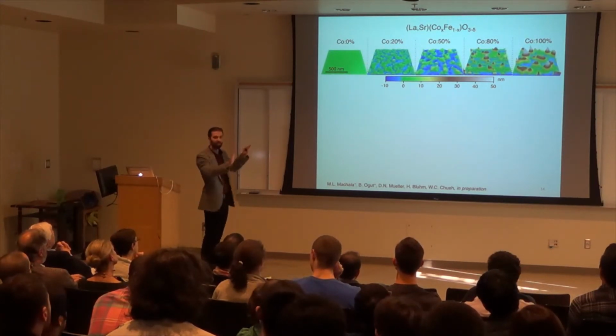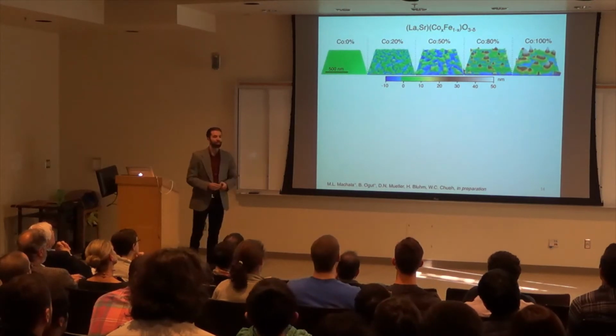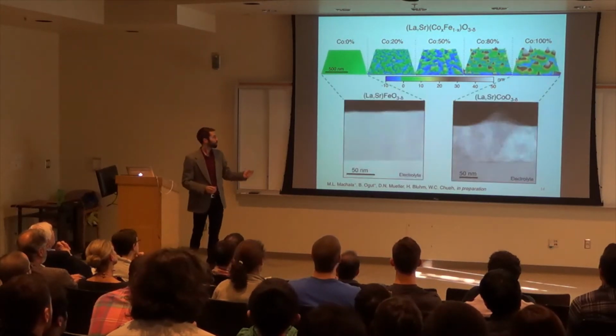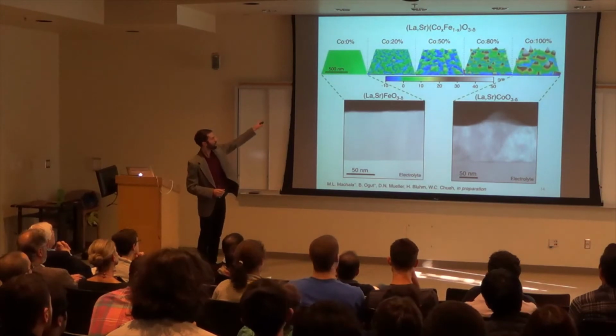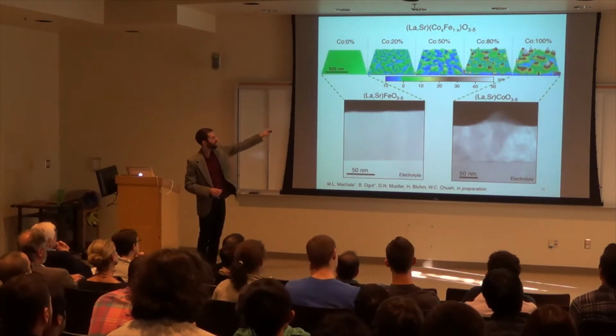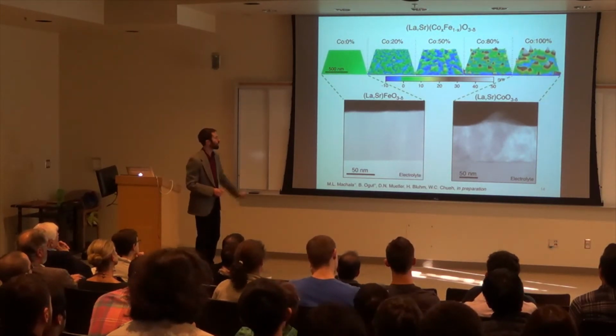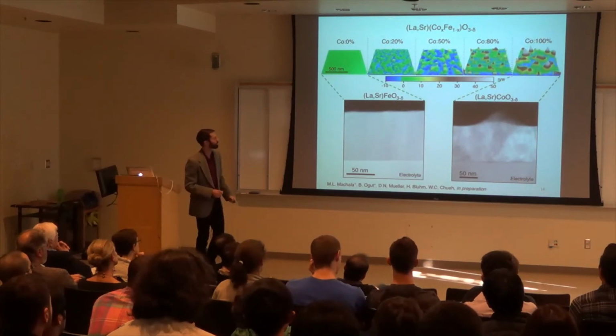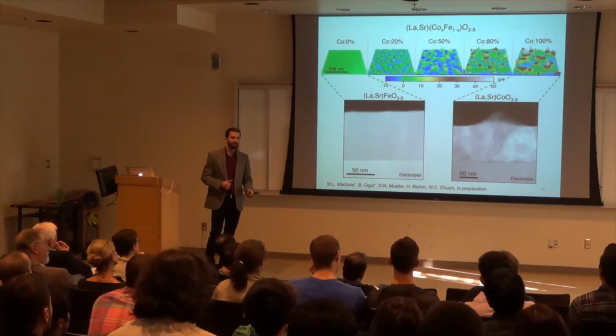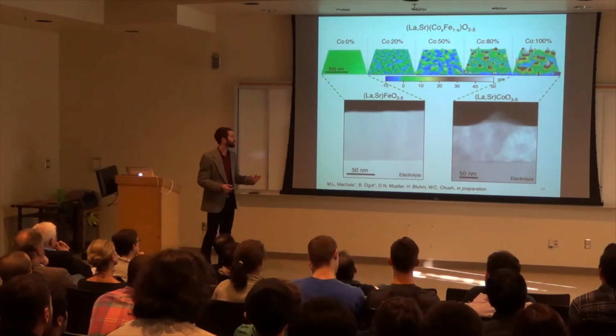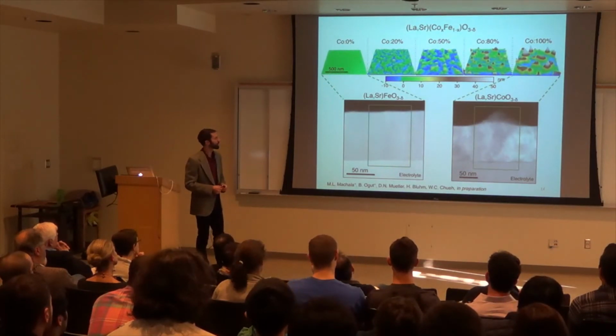So what we're going to use now is a technique where we can basically slice these surfaces in half and look at them from the side. And we use scanning transmission electron microscopy for that. So here, we just focus on the end members, the one with only iron and the one with only cobalt. Okay? And we can see that we have one of those bumps there on the right. We can do chemical mapping using what we call STEM-EDS and focus in on one specific region to see, okay, where the cation is located in these areas.